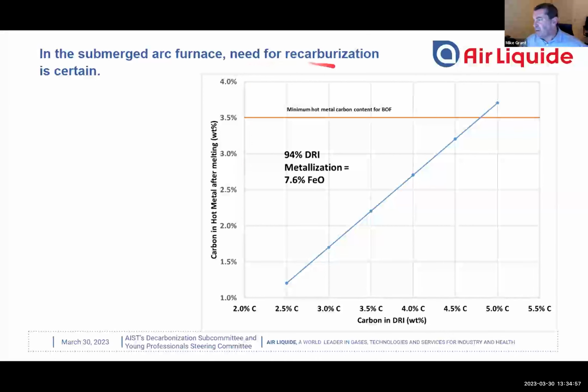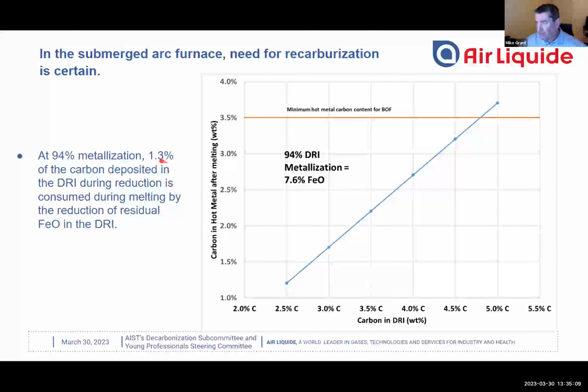So evidently there's going to be a need, whether it's a high carbon DRI or a low carbon DRI, we're going to need to get carbon into the process. We're going to lose about 1.3% of the carbon that was deposited in the DRI just through a reduction of the residual FeO that's there.